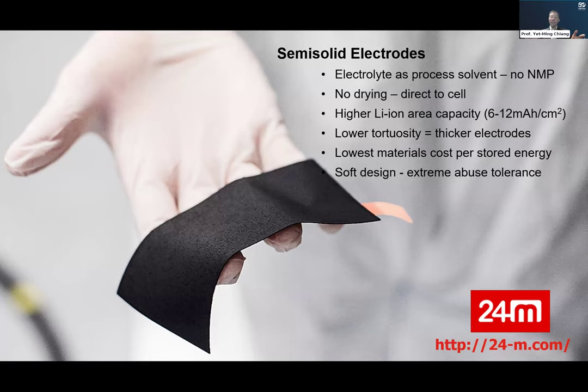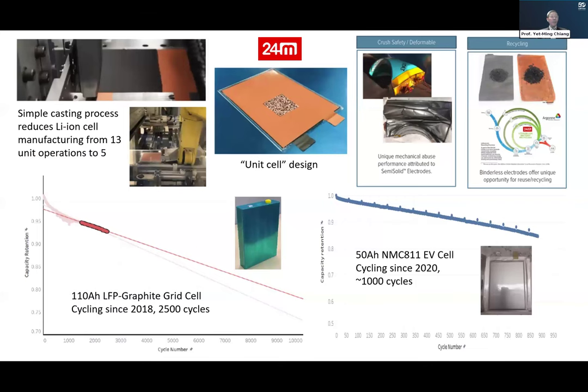And so this is a technology that somewhat quietly has been scaling over the last few years. And I'll show you a couple of snapshots here. So first of all, there's no coating line. Right? You've taken away the coating line. There's a casting process with what is a thick paste or slurry directly onto metal foils, with which you can build a cell. We call it a unit cell, which is a pair of electrodes, right? Which is encased in low-cost plastic. And then these cells have been proven out in both LFP chemistries, almost a decade ago, and more recently in NMC EV cells, for example, a 50 amp hour cell here.